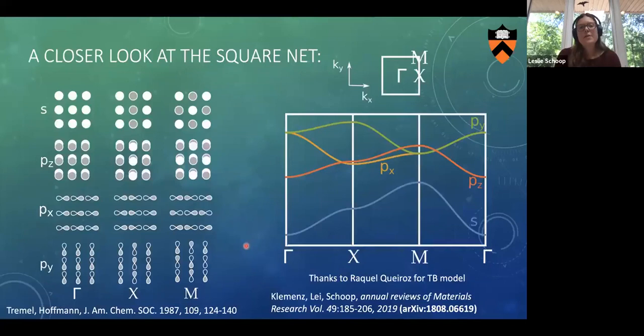So I want to understand the square net a little bit better. How does the square net result in this beautiful band structure and also in this hypervalent bond? Because if I now go back and do Roald Hoffmann's analysis of drawing orbitals in the square net, I get a band structure as is shown here. You could also just write down your tight-binding Hamiltonian of the square net and use some chemical intuition for the hopping parameters, and then you get a band structure like that. But this doesn't have these linear bands. So that was a bit confusing. It's like, huh? I understand my hypervalent bond argument, but now I don't understand this square net band structure.